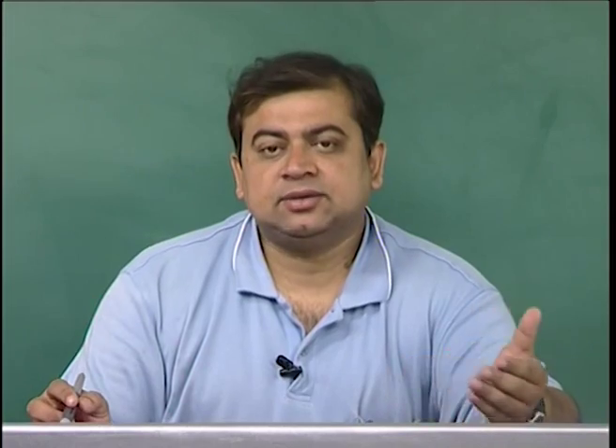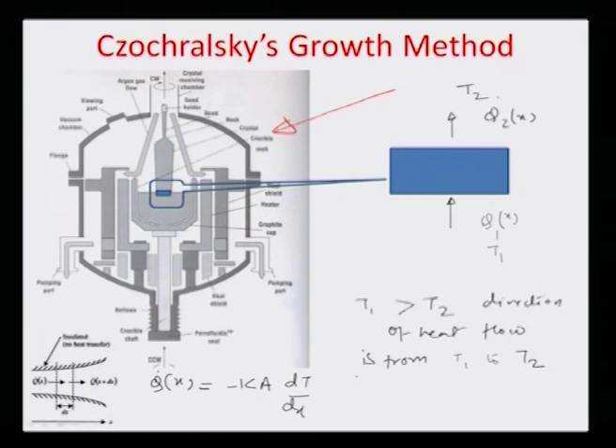Now let us do some mathematical modeling for this process, which can give us an idea of how the liquid to solid conversion can take place in terms of latent heat of solidification. Okay, and we can just do a simple one-dimensional heat flow analogy to understand the situation. So let's say you have a crucible here in this particular example, and we are considering this particular zone here, which is also called the zone of fusion. Okay, a zone of fusion because this is the zone where there is a presence of both states, the liquid state which is in the crucible, and the solid state which is a part of the seed which is getting withdrawn. And so it's a sort of semi-solid, semi-liquid zone that we are considering.